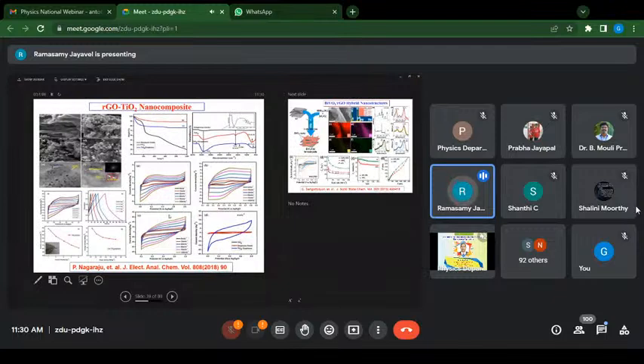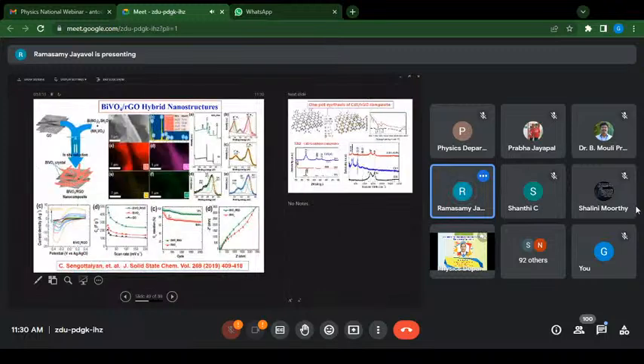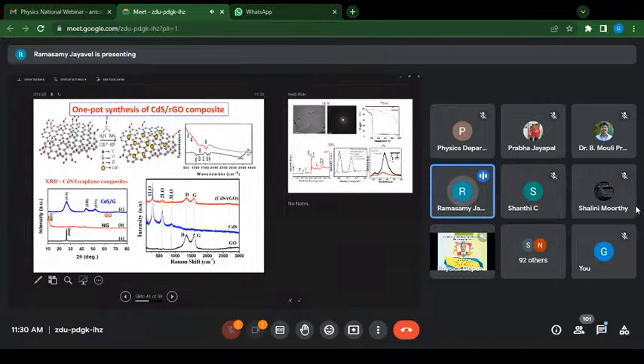And then we have just made a 2-electrode working supercapacitor with RGO and titanium oxide. And this is actually a different morphology. It's bismuth vanadate with one-dimensional morphology integrated with 2D RGO. This kind of combination has more stability, where the cyclic stability was very good. Having done with metal oxides, we also tried metal sulfides, like cadmium sulfide, zinc sulfide, and lead sulfide. These sulfides have the advantage that we can make very tiny particles, so that they can be easily integrated with the 2-dimensional layers.